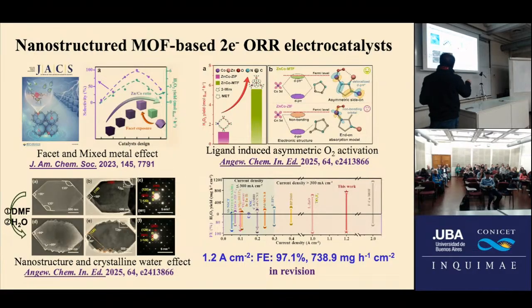So here I have several examples showing that increasing the anisotropy can improve the electrocatalytic performance. This is one example showing that if you only have the cobalt or zinc-based ZIF material, they are not good catalysts. Only when you mix both zinc and cobalt together can you achieve a high performance. Moreover, you can see at the same zinc and cobalt ratio, you must have this 100 facet exposure, but not this 110 facet exposure.